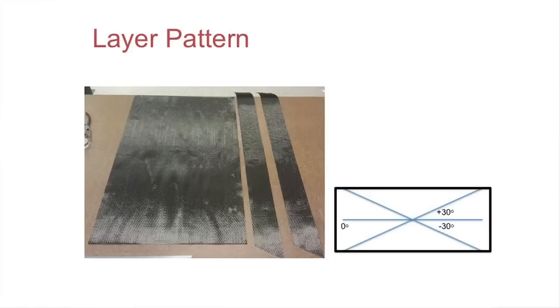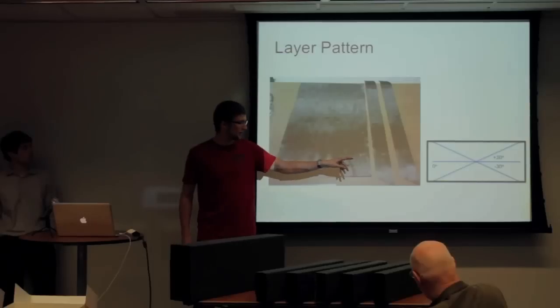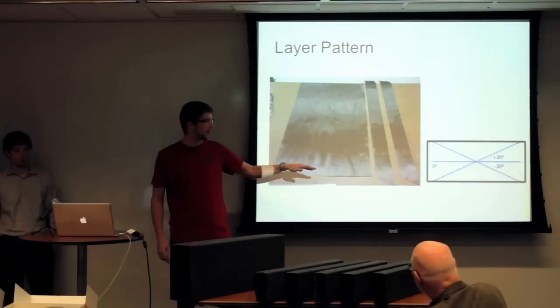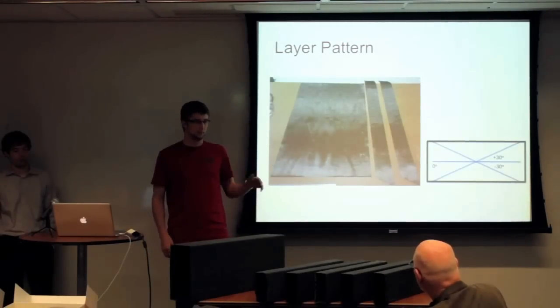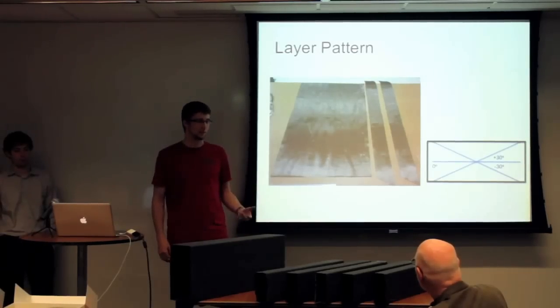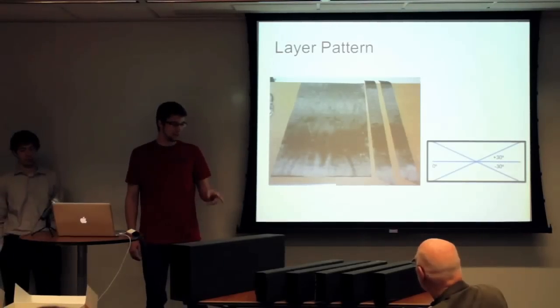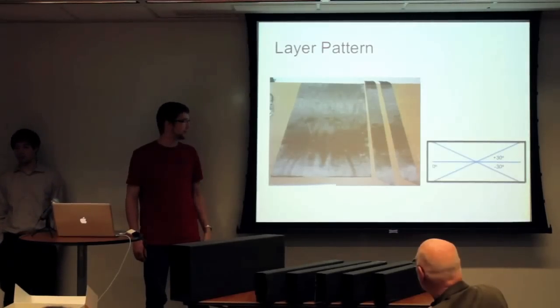From the ANSYS, we ran several iterations to figure out which combinations of layers would give us the best rigidity for the applied loads. The solution we came up with was a 5-layer approach for all of the pieces. It's really important that the layers are symmetric, so what we used is plus 30, minus 30, and 0 degree, and then you go minus 30 and plus 30 again. That way you have a symmetric layer, and when the carbon fiber cools after you bake it in the oven, each side has the same stress, so the carbon fiber doesn't warp. When we fabricated our first strips, we didn't take that into account, and we had potato chips as a result. We had the 5 layers for these, so these stay perfectly straight.